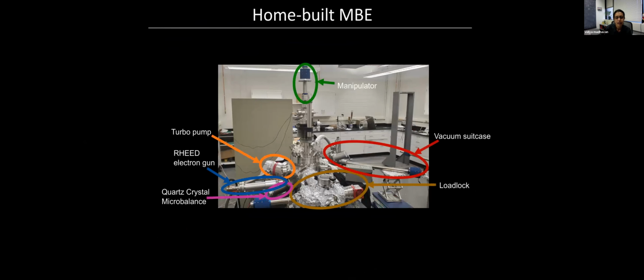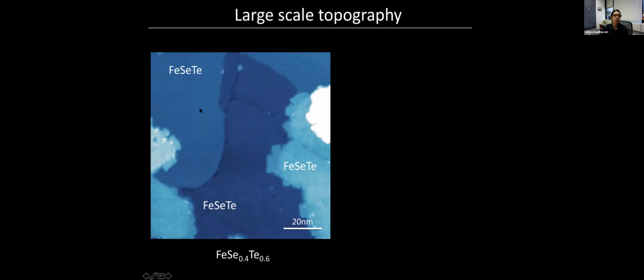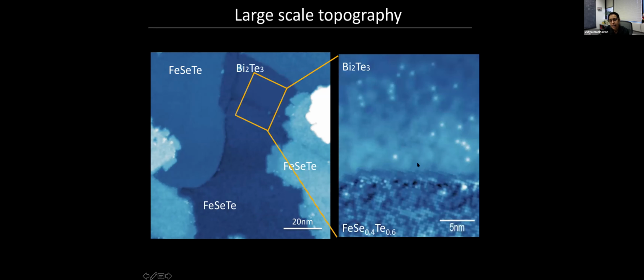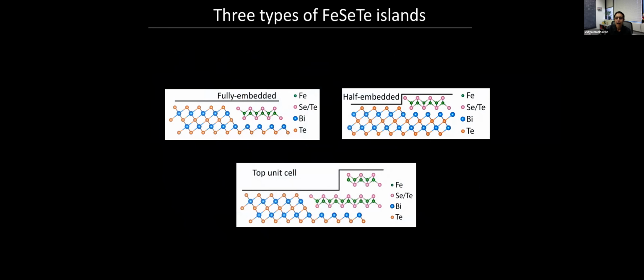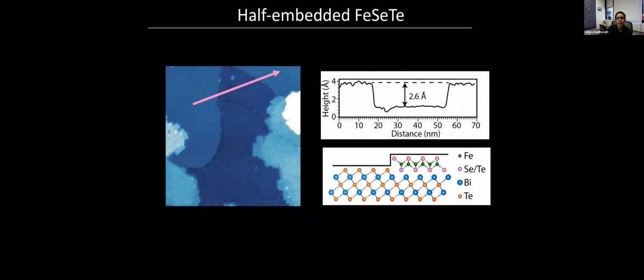I don't know if I'm going to have time to go through this whole thing, but let me just show you a few slides because this is very interesting. So we used our MBE system to grow FeSeTe on bismuth telluride. So here's bismuth telluride, right? And here's FeSeTe. You can see very clearly the hexagonal lattice associated with bismuth telluride, and this is one monolayer of FeSeTe. Now, this is pretty crazy. You don't know if this is superconducting at all. If it is superconducting, you don't know what the TC is, etc. But I'll show you that this thing is indeed superconducting.